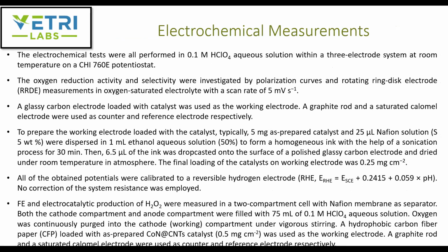The electrochemical measurements were all performed in 0.1 molar perchloric acid in a 3 electrode system, and the oxygen reduction activity was measured by RRDE in oxygen saturated electrolyte at a scan rate of 5 millivolt per second. Here they coated their glassy carbon electrode with the prepared catalyst. They made a catalyst ink with 5 milligram catalyst, 25 microliter of Nafion solution and 1 ml of ethanol to form a homogeneous ink, and then they drop casted 6.5 microliter of that ink to get a loading of about 0.25 milligram per centimeter square on the working electrode. They used a graphite rod as the counter and a saturated calomel electrode as the reference electrode. They used the pH to convert the electrode potential to the reversible hydrogen electrode scale, and they did not do any correction for the system resistance.